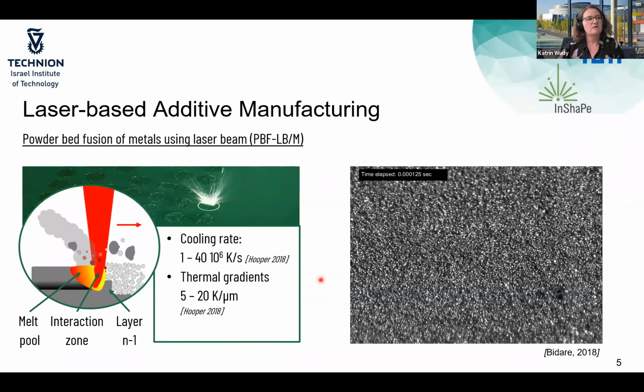So this was the topic of process speed, but I explained to you the aim that we would like to get a smoother processing, so a decrease of process dynamics. What you can see in the video in a few seconds at the top is the typical process with a Gaussian beam profile. It's a video camera which was installed on axis, so you see directly the laser spot here, and you can quite nicely see the balling effect. These little balls are significant for the balling effect, so it's not a stable process at the end. And now for the same parameter combination, you see the ring-shaped beam profile.